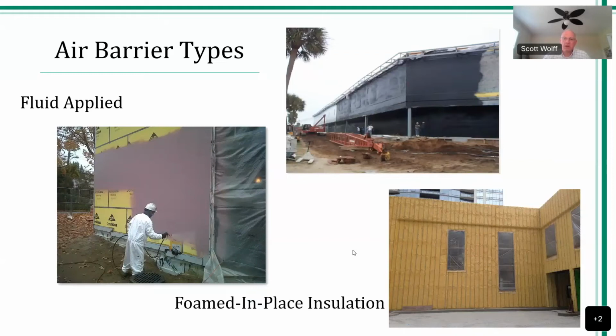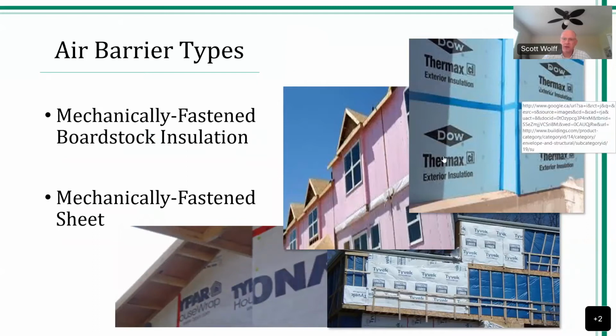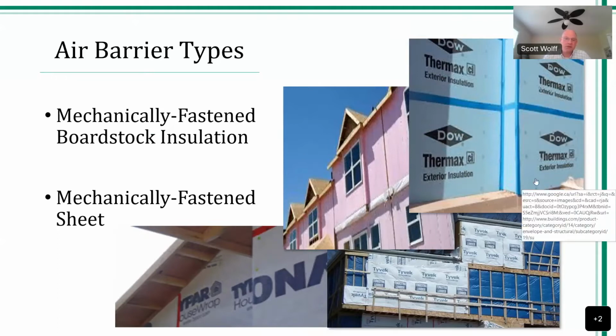If we consider a steel framed building, a mid-rise or even a high-rise that's subject to a lot of wind forces, frankly, all three modes of axes of movement, X, Y, and Z axis movement, this foam doesn't like to move. I used to be in the gypsum world, and I've actually seen gypsum panels fracture in the field areas of the panel, the 4x8 sheets. So if we do not have an elastomeric membrane behind, say, a rigid piece of insulation, and this is now acting as all four control layers, we've basically compromised our entire envelope. But if the rigid insulation does fracture, but we do have a membrane behind it, we've still got a plane of air tightness, something that's going to have 400 to 800% elongation that can potentially accommodate some of those differential movements buildings are inevitably subject to.